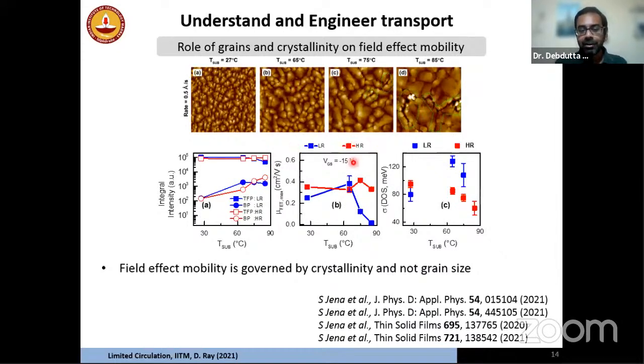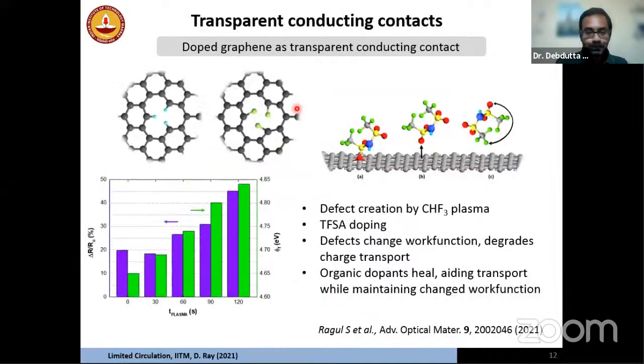So for example, this is for a material which has nearly the highest mobilities, not the highest, but nearly. As you can see, the mobilities are not very high, right? So this is 1 centimeter square per volt second. So you can see that the mobilities are much smaller than what you see, let's say, in silicon. However, it works because we are working with very thin samples, 30 nanometers, 20 nanometers, something like that. And hence, once you engineer the carrier transport, then you can design your OLED, right?